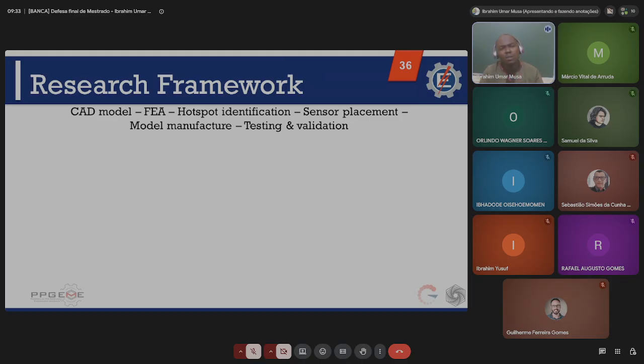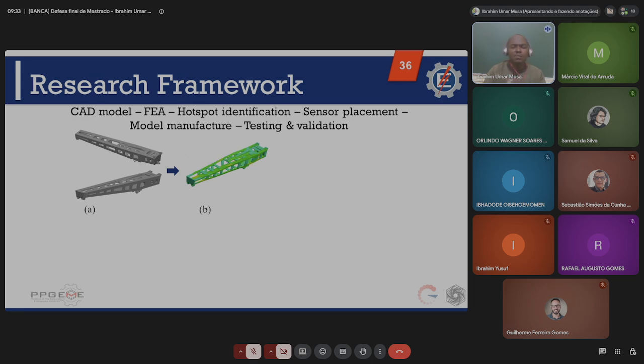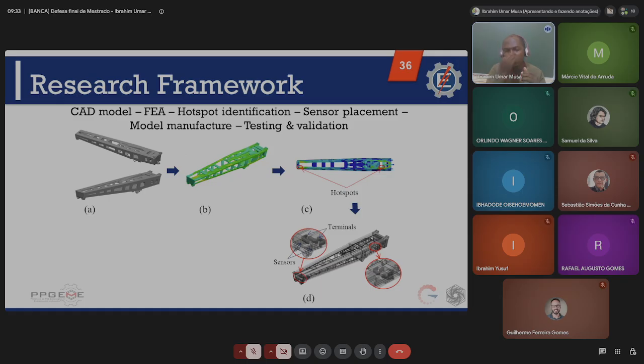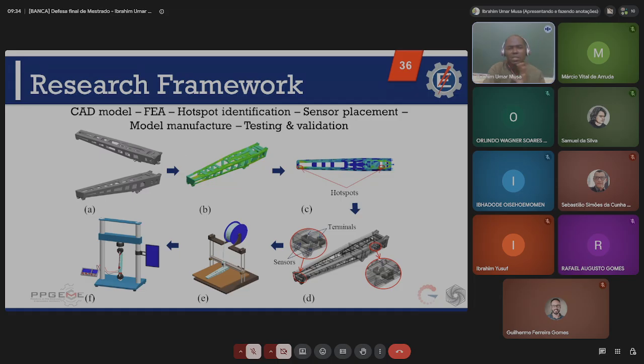The framework we used followed a six-step methodology, starting with the CAD modeling of the pylon structure, followed by the finite element analysis. From the finite element analysis results, we identified the hotspots, and on the identified hotspots, we systematically placed our sensors, and the structure was then additively manufactured and finally tested and validated.